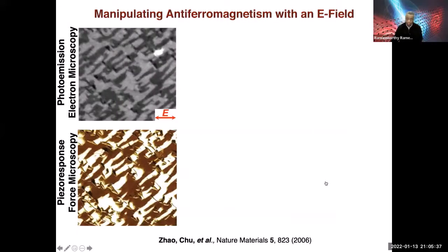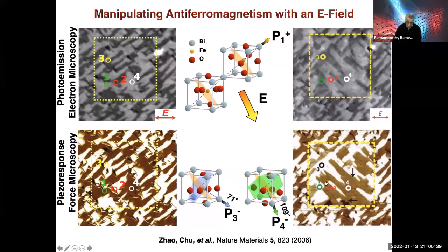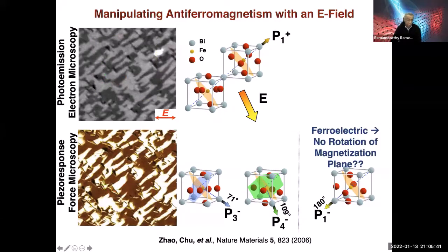And so the first experiment that we did, I went too fast, back in the 2005-06 timeframe, was to look at the ferroelectric domain structure of one of these films. This is actually pretty complicated. This image here is a piezo force microscopy image, and you can see contrast due to ferroelectric domains. You can take that to the synchrotron source and do something called photoemission electron microscopy. And what we see is that these domains, which map out the antiferromagnetic order, look very similar.